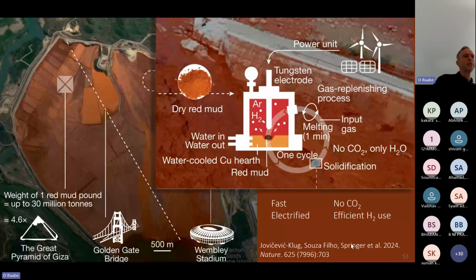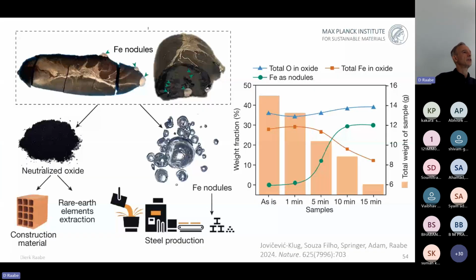And in this recent paper, we could show that in this plasma-based reduction with very lean use of hydrogen, you can turn also this red mud material very efficiently into pure metal and into a neutralized oxide material that you can use in construction. So the use of red mud is, of course, well known in the literature, but this is a very efficient one-step process to turn the entire material into two separate industry materials that can be used. And it's also very, very fast and economically efficient.